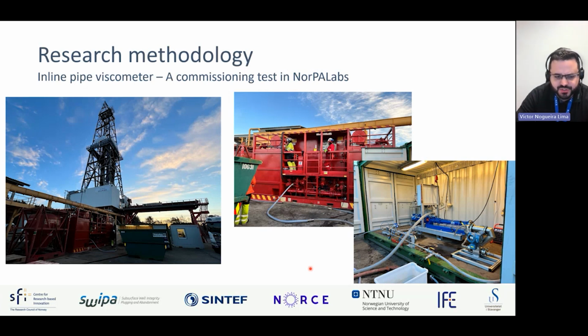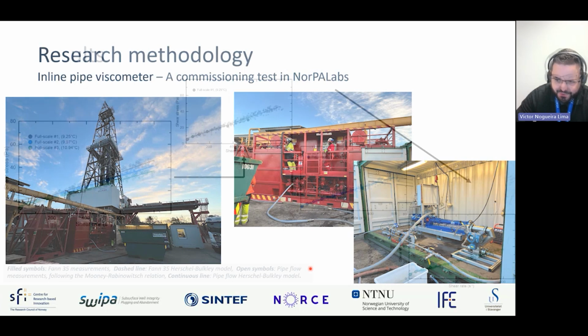This commissioning test was a test that we did using the U8 well, and this U8 well is placed in the UiS test center. In this commissioning test we used an offshore style batch mixer, and we connected the pipe viscometer setup to this offshore style batch mixer. So the idea was to mix a large amount of slurry, then do some sequences using the pipe viscometer and check if the pipe viscometer could really fit this type of setup, and if we could really do the measurements while doing the mixing and conditioning of the slurry.